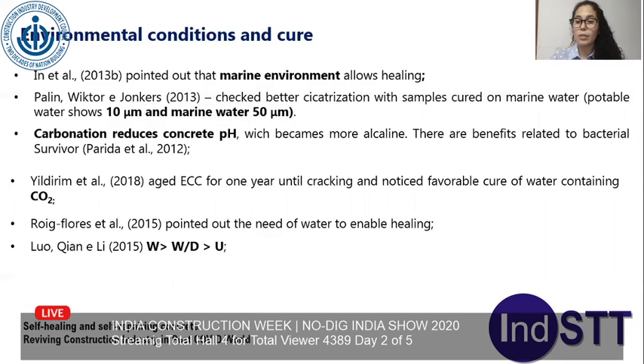Related to carbon dioxide, carbonation reduces the pH, which is better for bacterial survival. Yildirim and other authors aged ECC for 1 year, and they also discovered that carbon dioxide works better as a cure condition. Roig-Flores says that there is a need for water. And Luo, Qian, and Li say that a wet condition is better than wet and dry, which is better than only a humid condition.